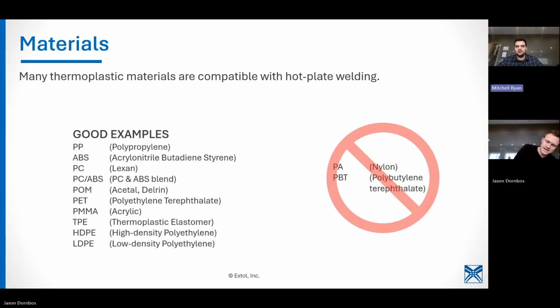PEEK. Great question. I personally have not seen PEEK be hot plate welded. We have limited experience with welding PEEK in hot plate. We've tried to process PEEK a lot of different times. Very high temperature. To be determined. I don't know if anybody on the call has experience trying to do hot plate welding with PEEK, and you want to chime in. But as far as I know, nothing about PEEK makes it totally unweldable. It's just a very high temperature, so it would be a challenge. Yeah, and kind of a sharp glass transition zone too. It's a challenging material for a lot of different welding applications.